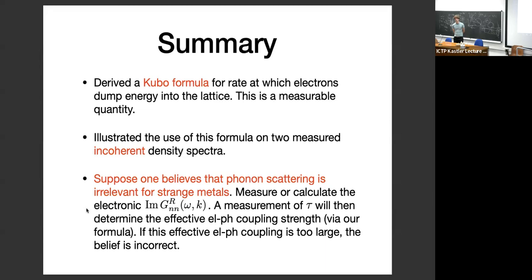Your assumption, when you wrote down your equivalent, if you want, for the Allen formula, is that you can get tau because the relaxation to the phonons is happening much faster than everything else. Slower. And usually there is an additional assumption, which is that diffusion is irrelevant, and that's why you first get its decay when the lattice and the electrons equilibrate, and then there's some slower relaxation process by diffusion. This is actually, I think, in Allen's paper. But if you have incoherent metals, can you really neglect the fact that your electrons are diffusing heat themselves to the boundaries rapidly?